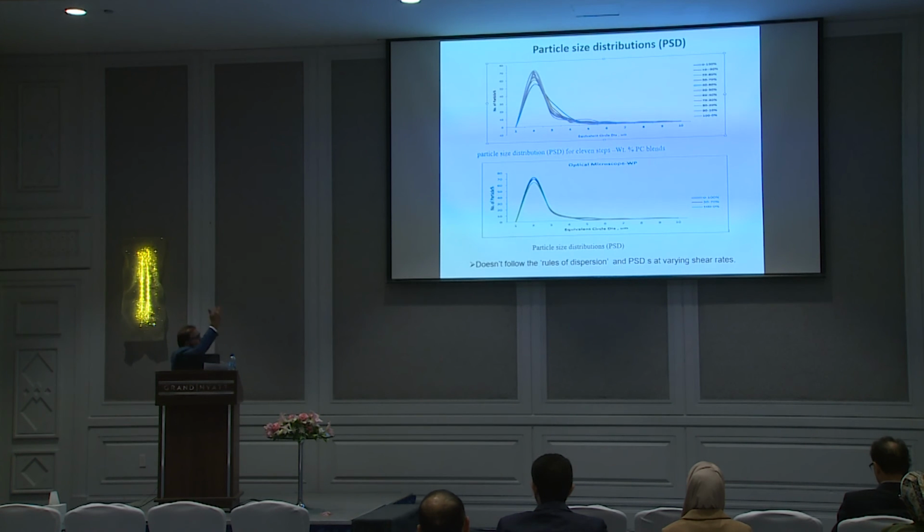So for the same steps of variation of content, we ran it under dispersion. The same material, I put the sample under the microscope, got the histogram data, and drew it, and it shows that it is also not following the dispersion distribution for both. Then I took another sample from the highest reading, the lowest, and the middle in order to see the effect of the dispersion.